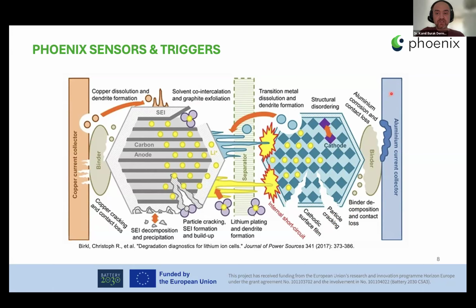When it comes to the current collector for the cathode side, aluminum is widely used, and aluminum corrosion and contact loss can happen between the binders and the current collectors. Since there is a contact loss, it increases the internal resistance, leading to a huge and dramatic capacity fade.